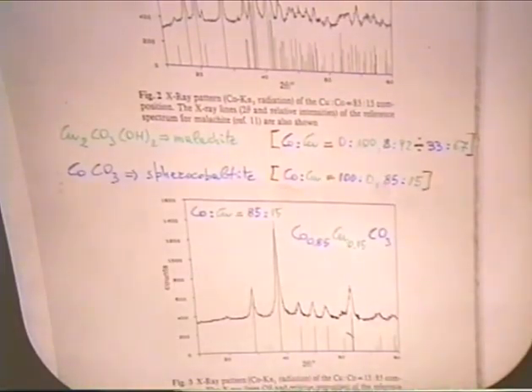For the cobalt copper 85:15 composition, namely when just a small amount of copper was added, the X-ray diffraction analysis showed that the copper formed a solid solution in the spherocobaltite lattice. On the other hand, for the compositions 8:92 and 33:67, the X-ray diffraction showed that the cobalt was present in the crystalline lattice of the malachite. So also in this case we obtained the solid solution.